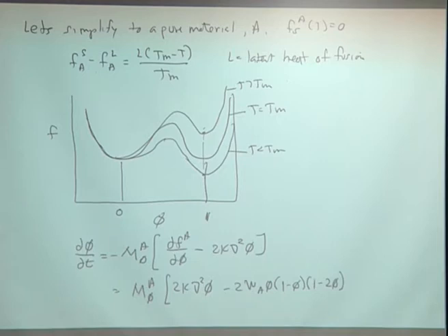So again, you're thinking too much like a physicist. Because what it says is kind of important: you notice there are spinodals here, right? And so this model says, if you're thinking in terms of a physics model, that you get a spinodal decomposition from a liquid to a solid. And that's absolutely impossible, because there's a difference in crystal structure, exactly as you say.